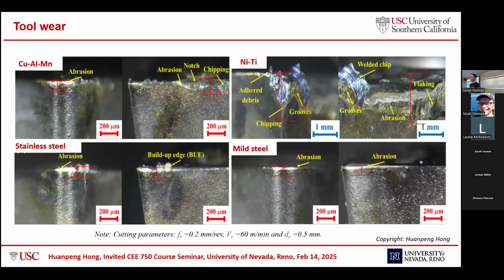So here's a comparison of the tool wear. From this figure, there are materials: the copper aluminum manganese alloy, nickel titanium, stainless steel, and mild steel. We see that machining copper aluminum manganese alloy is almost comparable to machining stainless steel. It's a little bit higher than machining mild steel, but it is only around 5%, or only 1/20, of that of machining nickel titanium alloy.